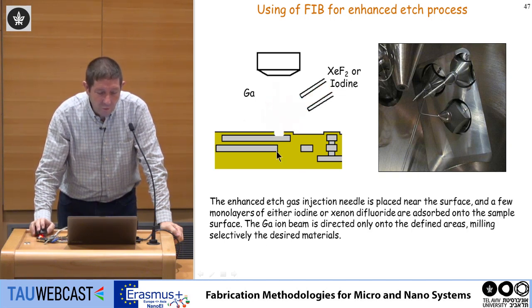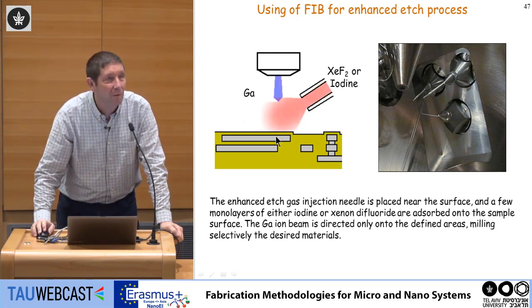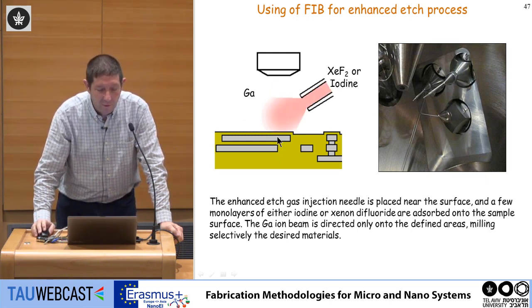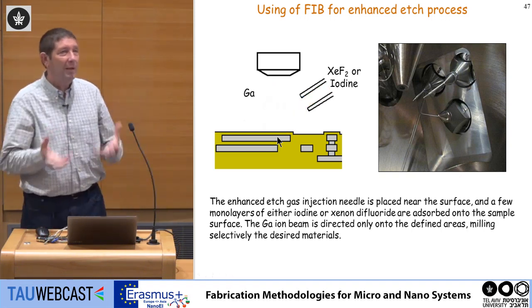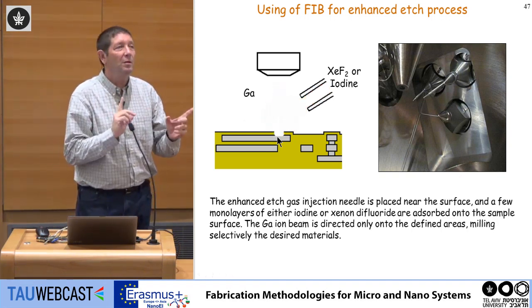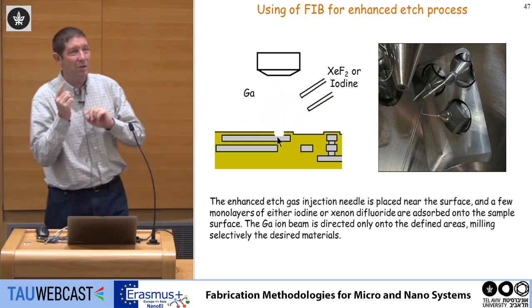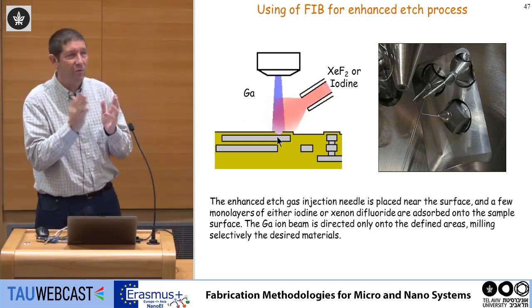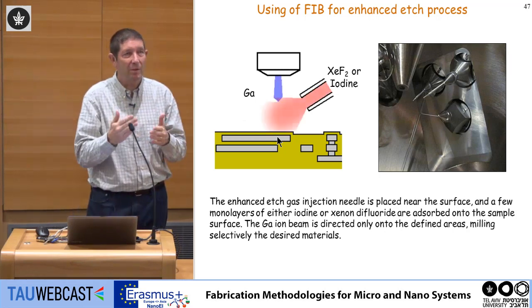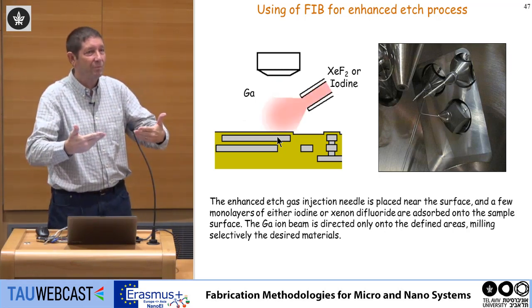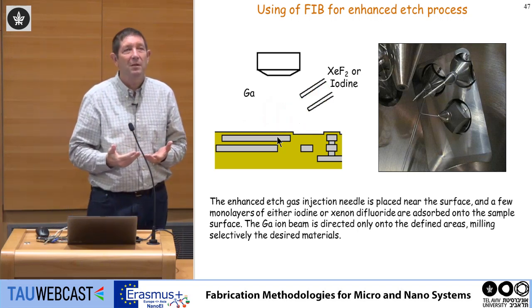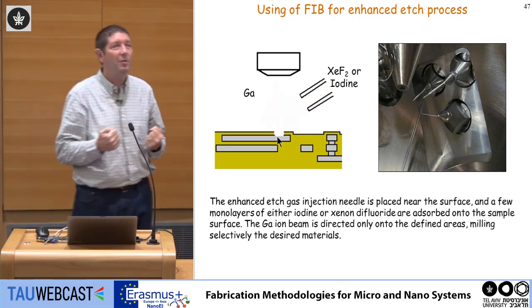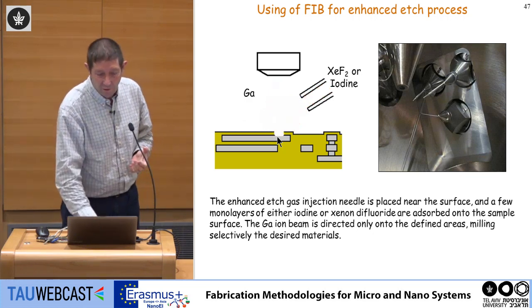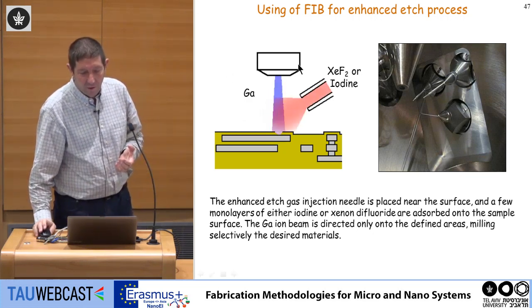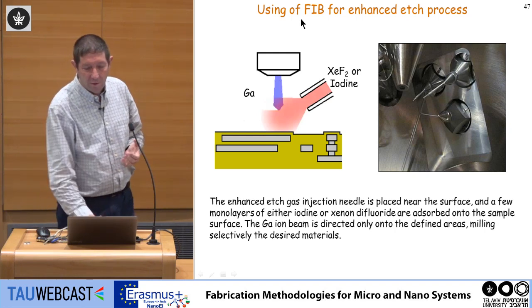By the way, according to this explanation, you can also do enhanced etching, but you can also do enhanced milling, because once this material reaches the surface, the milling rate is faster. And these are the two models for enhanced etching. One is that the etching is faster because of the enhanced energy of the fluorine or the iodine. And the second one, if you have iodine adsorbed to the surface, it makes the milling of the surface much easier because it breaks some of the bonds on the surface. Either way, some people use FIB to enhance etch processes.